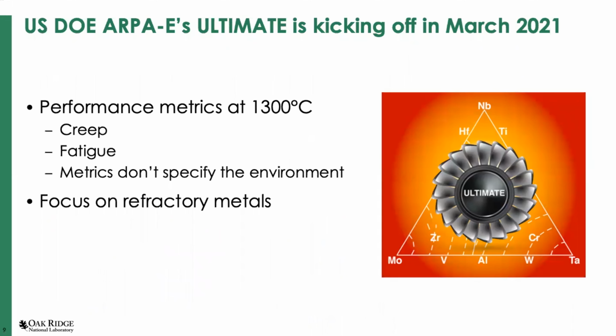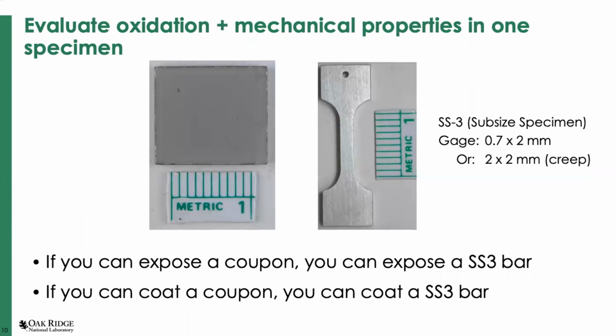So what has interest right now is that ARPA-E is about to kick off their ultimate program, and they want to look at materials for 1300 degrees C. They have metrics to achieve for creep and fatigue at 1300 degrees C, but the metrics don't specify the environment. So I am part of this program, but just for the mechanical properties testing and not so much for environmental effects. And they are going to focus on refractory metals, as you can glean from their logo. And so the point I want to make about how we assess things is that we can very easily replace our coupons with tensile specimens if we want to.